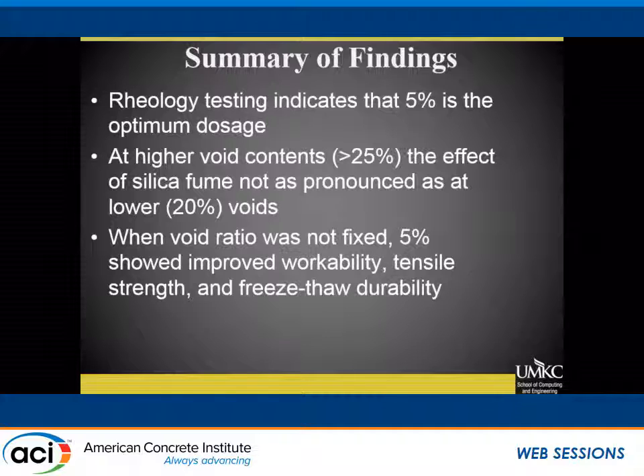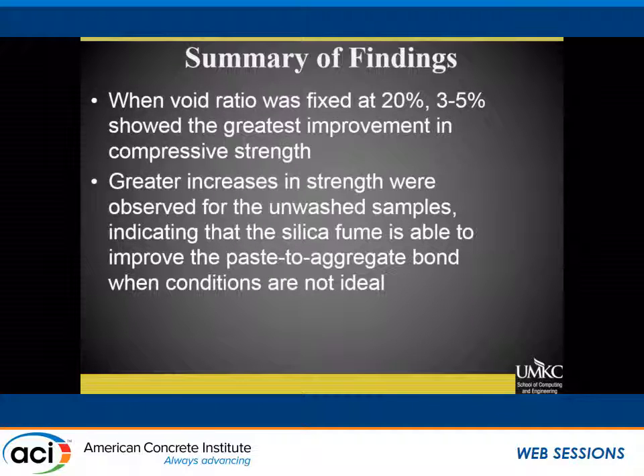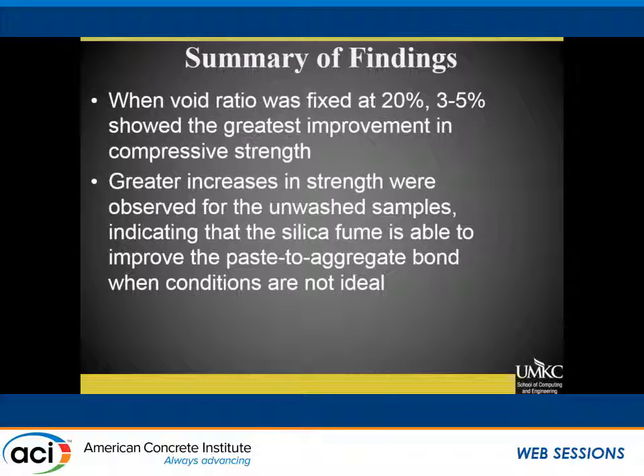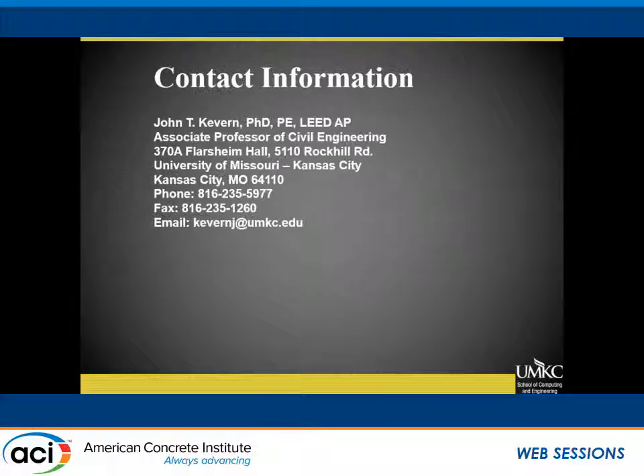When we didn't fix the void ratio, so what we do typically in the field, 5% had a little bit better workability, which resulted in better strength. When we fixed our void ratio, to look at it, 3 to 5% seemed to be the best. We did get an improvement in strength. We did get, for our gravel samples, improvement in abrasion resistance. For the limestone samples, couldn't really see any differences. So, all right.